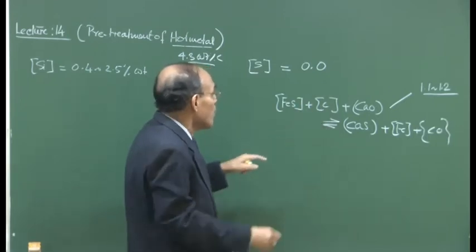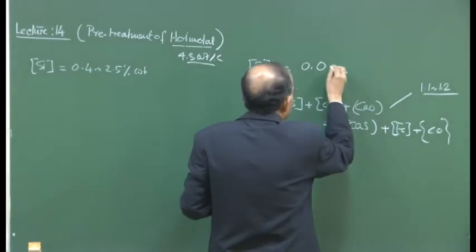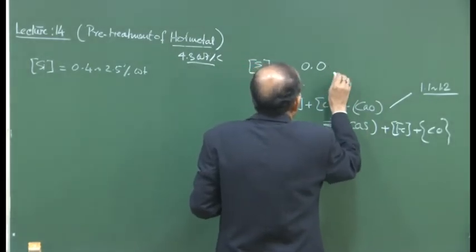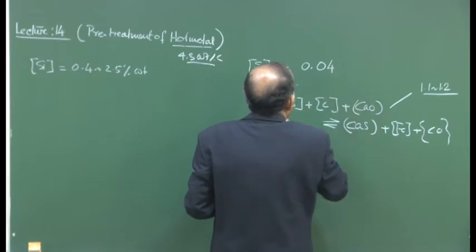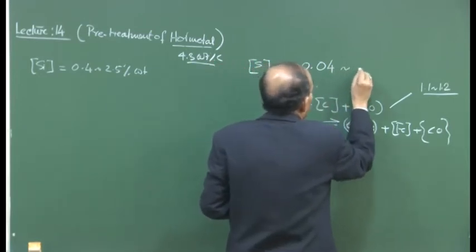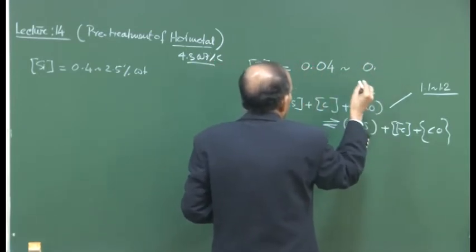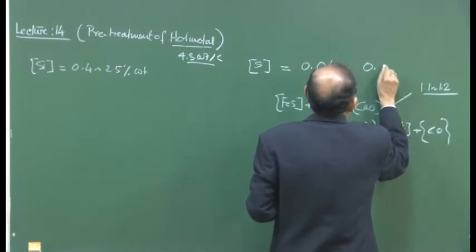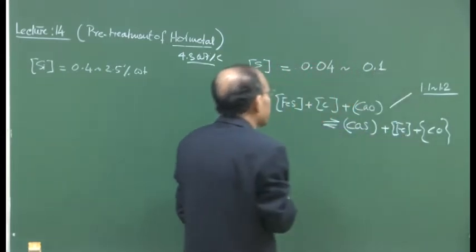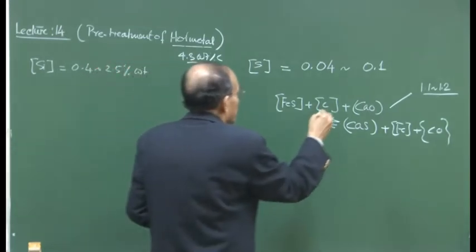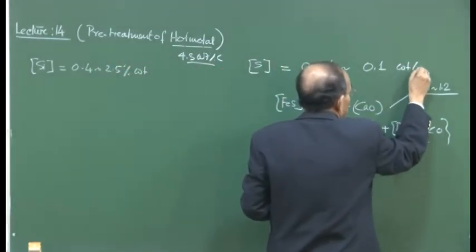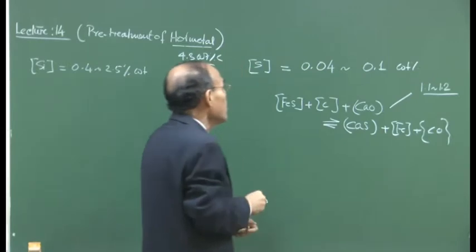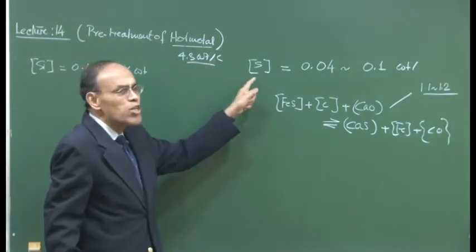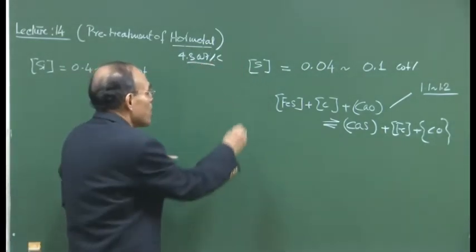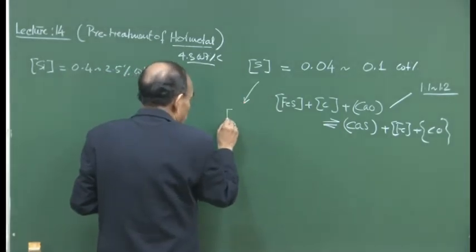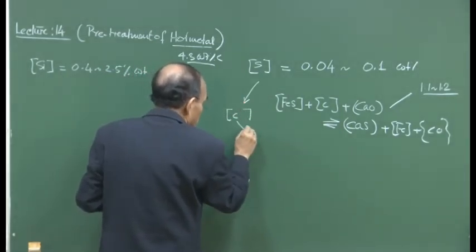So, in the hot metal, sulfur can go from a range of 0.04 to about 0.1 weight percent or something like that. And this sulfur, what is the major source of sulfur? The major source of sulfur in pig iron or hot metal is the coke.